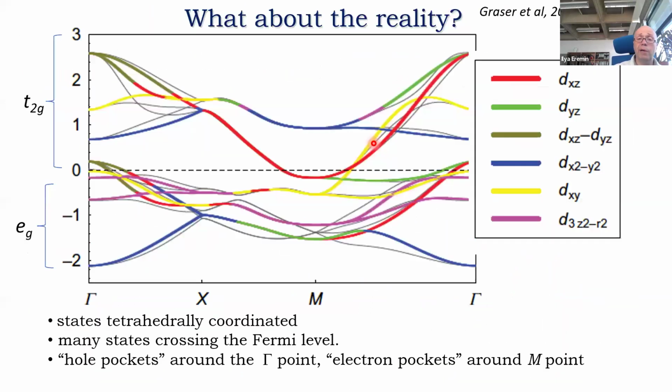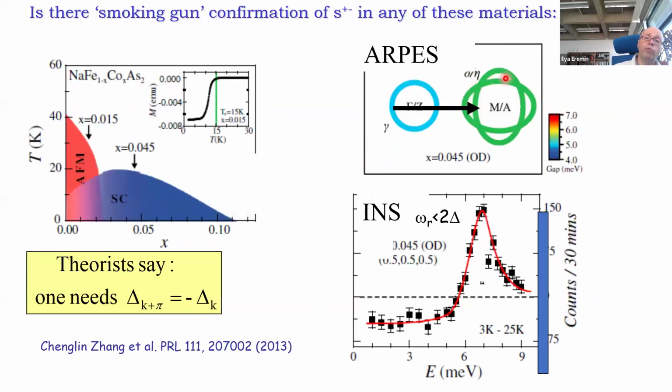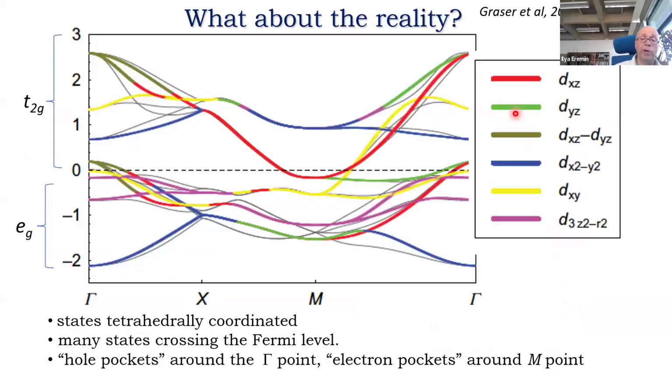So if I again come back to the Fermi surface, imagine you move on the Fermi surface, and then somewhere, for example, here, you have nodes, but these nodes are not a D wave. They can still be described by the irreducible representation of cosine kx plus cosine ky, just expanded. Near the M point, cosine kx plus cosine ky becomes cosine kx minus cosine ky. You understand? At pi 0, right? Okay, so that's still an S wave.